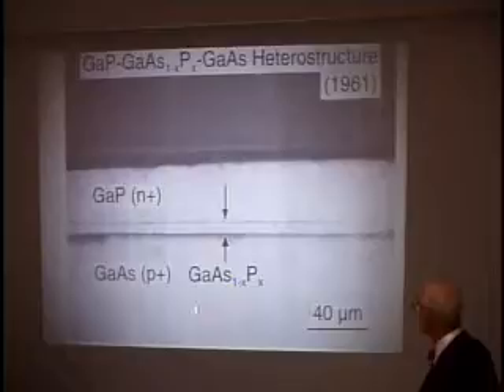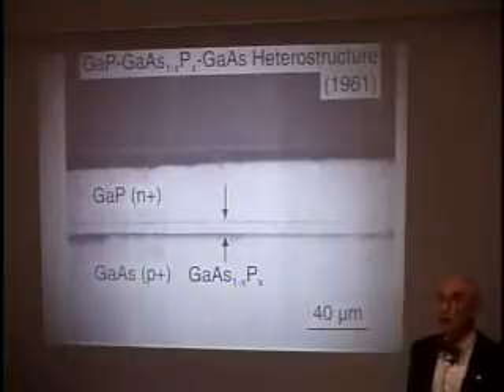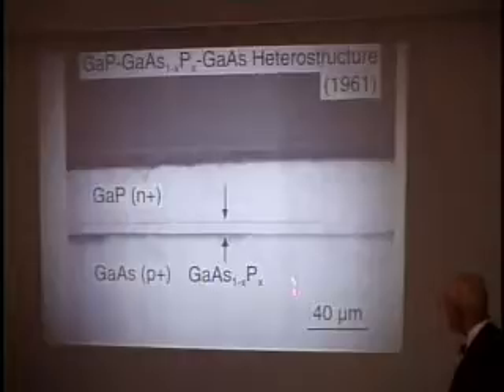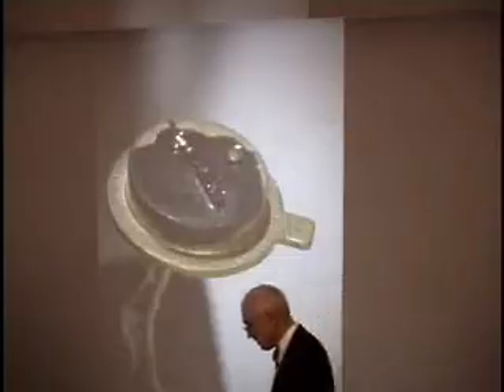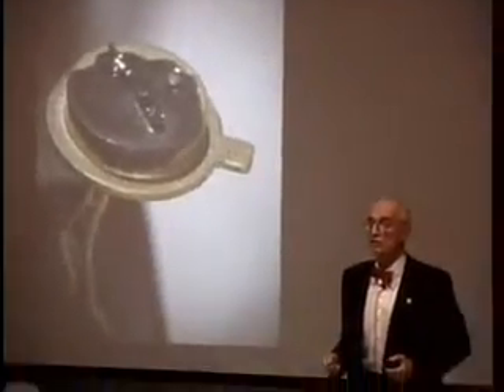In other words, again, heterojunctions and alloys and so forth before there was a semiconductor laser. But this is a material that goes up to higher energy out of the infrared into the red. And so when it looked like we could make, well, here's the material again. Gallium arsenide phosphide grown on gallium arsenide, and in the cross-section with visible light we could see through it. So since we know how to build things like this, in 1962 when it looked like it may be possible to build a semiconductor laser, in the group I was in at General Electric, we knew how to make gallium arsenide phosphide. The rest of the world didn't. They had some crazy ideas about how to do that, but we knew how to do that.